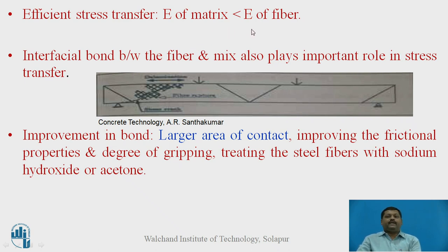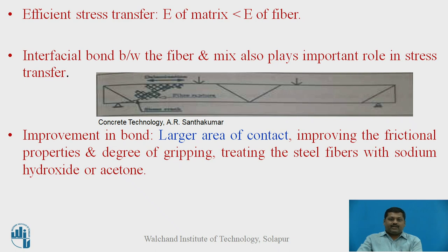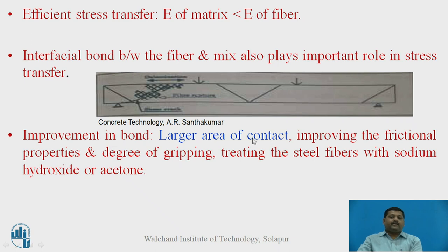For efficient stress transfer, the Young's modulus of the matrix must be much lower than the Young's modulus of the fiber. The bond between fiber and mix is also critical. As shown in the diagram of a flexural beam member — where a load is applied, a crack develops, and the fiber mesh arrests it — the interfacial bond plays a key role in stress transfer. Bond can be improved by increasing the contact area between fiber and matrix, which enhances frictional resistance and the degree of gripping. Bond can also be improved using sodium hydroxide treatment.